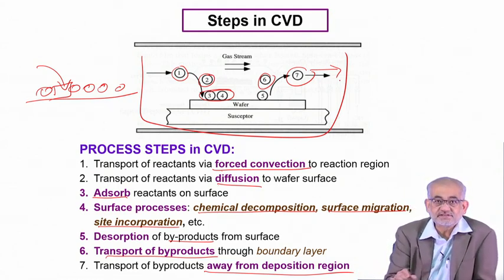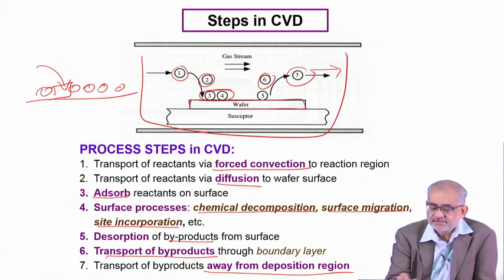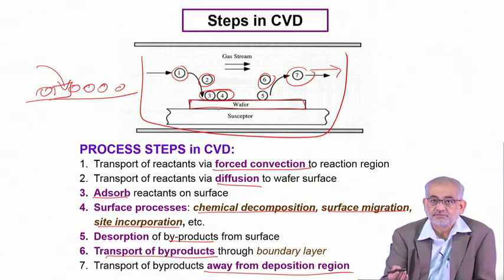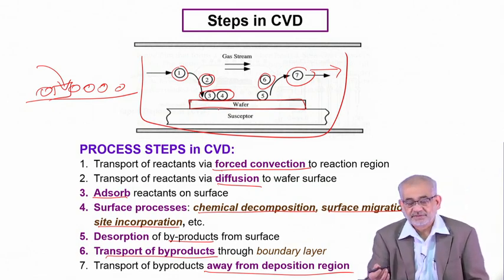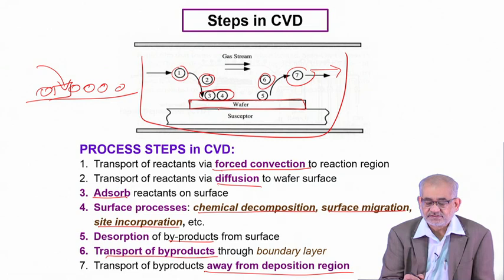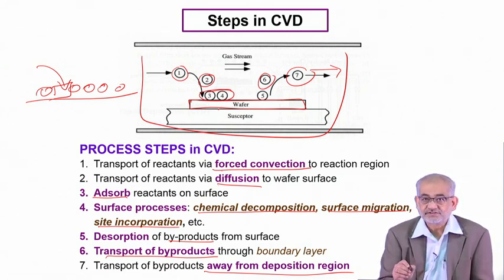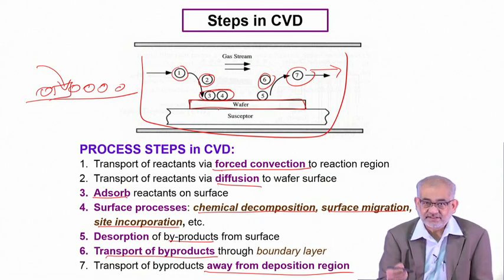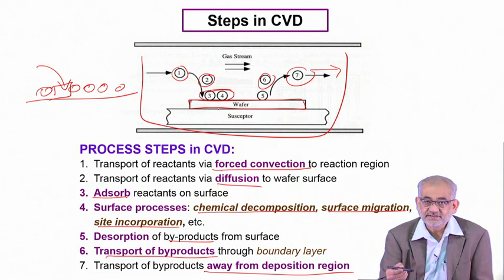This is the overall process — a batch process. The substrate, which in this case can be a silicon wafer, any other semiconducting compound, a metallic component, a gear component, parts which experience mechanical forces or relative motion, or a tool insert. Always remember that since the coating developed here is very thin, two things are very important: the surface topography has to be fairly smooth, not rough; and the adherence with the substrate should be very strong. Because the composition of this coating is fairly different from the substrate, the interface can be fairly sharp and that can lead to decohesion. So we need good surface integration.